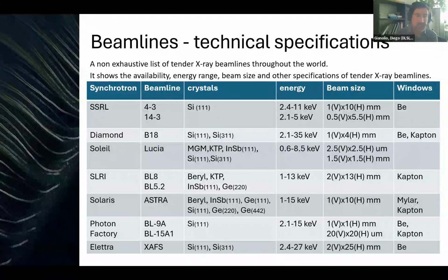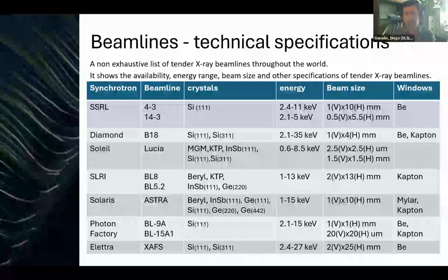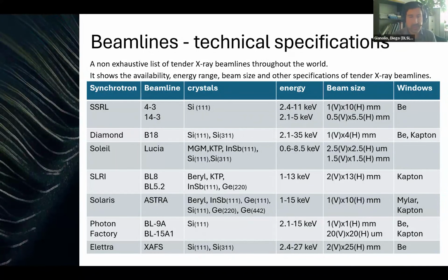And as you can notice, there are a few beamlines that can push more towards the lower limit, so they are more focused on the soft or tender, and other beamlines that maybe are more dedicated to hard X-rays, but they also have the possibility to collect tender X-ray spectroscopy data. And also in terms of beam size, there is a good variety. There are some beamlines that have a micro beam, so they also allow the possibility of doing some mapping fluorescence experiments, and others that instead have a very wide beam that might be useful to overcome inhomogeneities of the sample and give a bit more stability and collect a good XAFS.